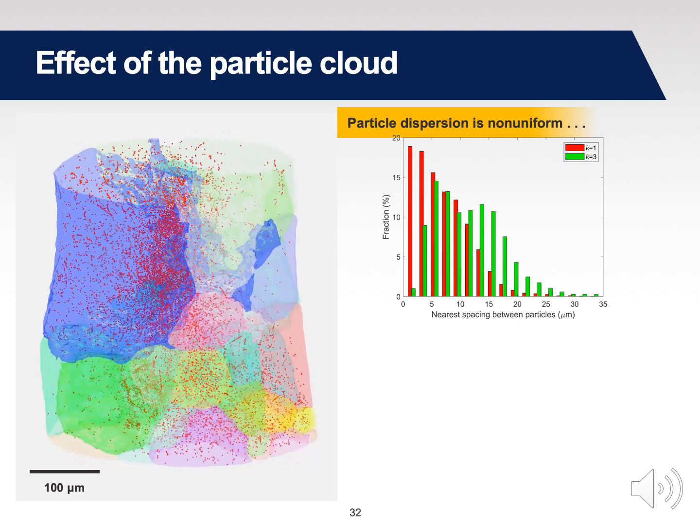Of course, this would indicate that the particle distribution is truly non-uniform and also non-random. If it were uniform, you would expect to see a single spacing between particles and a single peak in this distribution. You also see here that if we were to plot the third order neighbor between particles, so these are the red specks here, the third order nearest neighbors are indicated in the green.